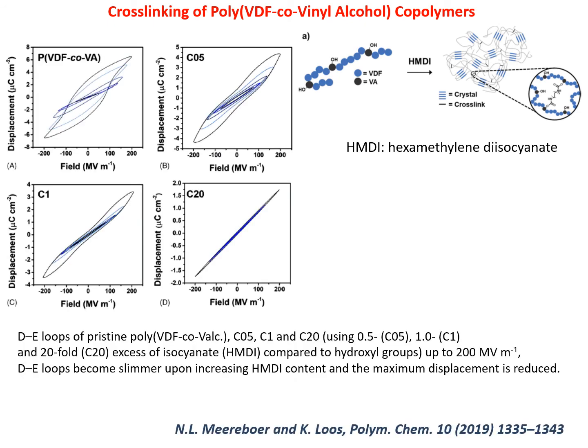And these are a physicists' group, so they study the DE parameters, and they show that without any cross-linking, you have a kind of ferroelectric system, while as soon as you increase to 5% HMDI, or 1% HMDI, or 20% HMDI, you have different profiles, even going to a kind of anti-ferroelectric behavior.